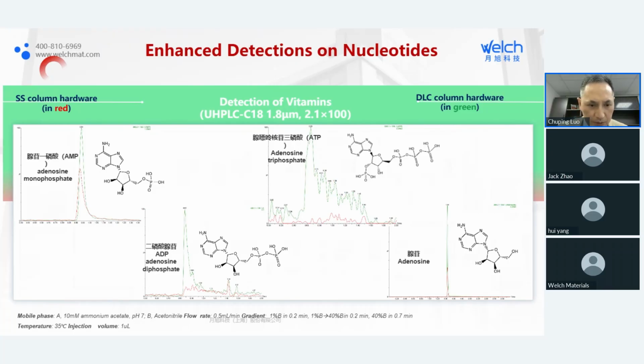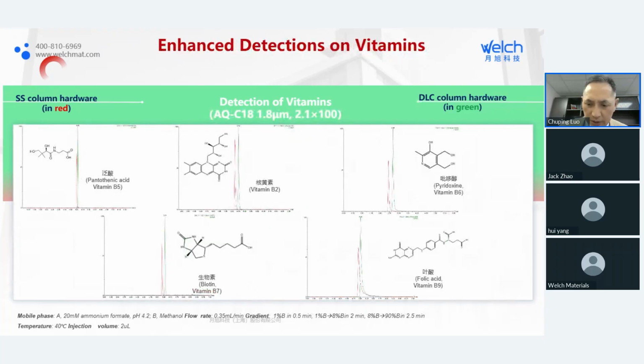Next, about vitamins. In this case, it's just an acid, with one acid group. But even with one acid group, you see a little bit improved signal with DLC hardware. And then this is vitamin B2. You see the improvement again. Vitamin B6 improved. Vitamin B7, the signal improved. Vitamin B9 also improved. So clearly, if you use the normal column hardware, stainless steel, you still can do the job. But if you want to detect trace amounts, it's better to use DLC column hardware.